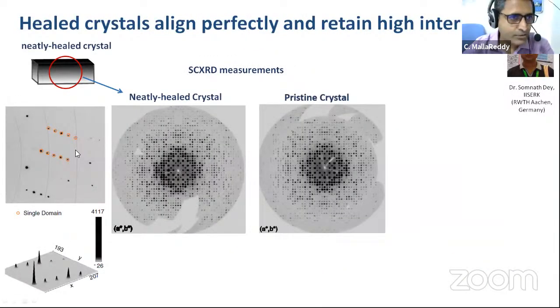We also looked at single crystal data from the nicely healed crystal, and we found no sign of fatigue in these crystals. X-ray is not a very good technique to know local changes, but on average it tells that it is still a very good crystal. You can get perfect diffraction data from it, and you can solve it. You don't find any difference between pristine crystals and neatly healed crystals. So you see the diffraction patterns. Even at higher angles, we found beautifully sharp peaks. That tells that at the level of X-ray, at least, you don't see any sign of damage in these crystals.